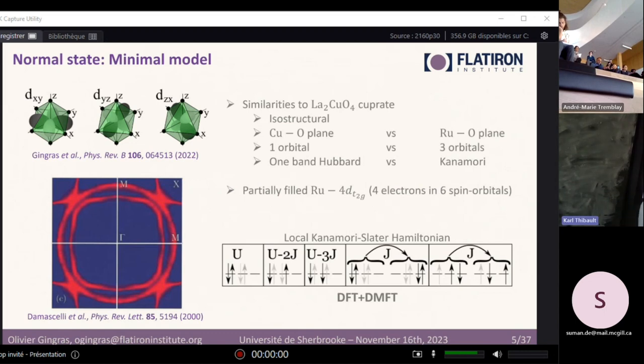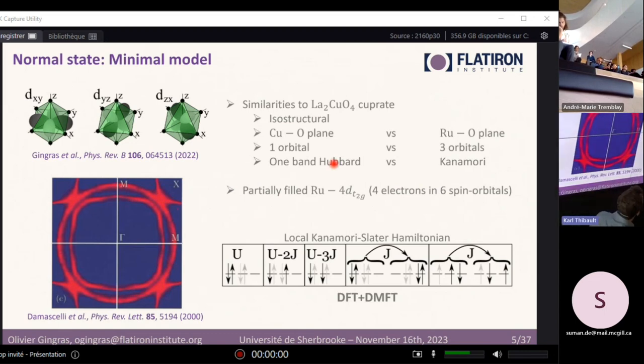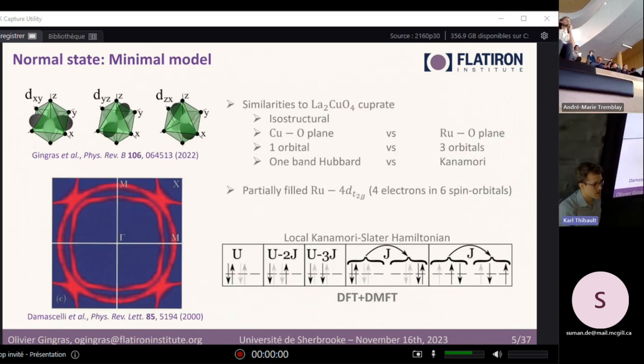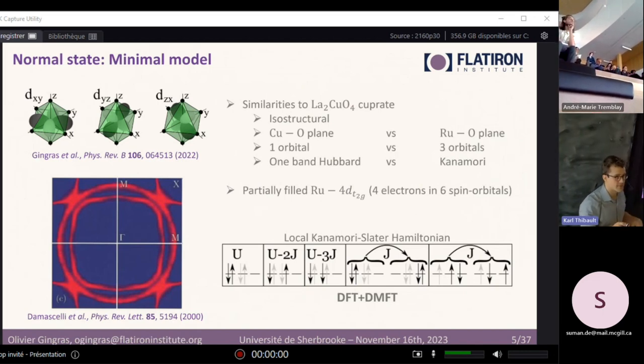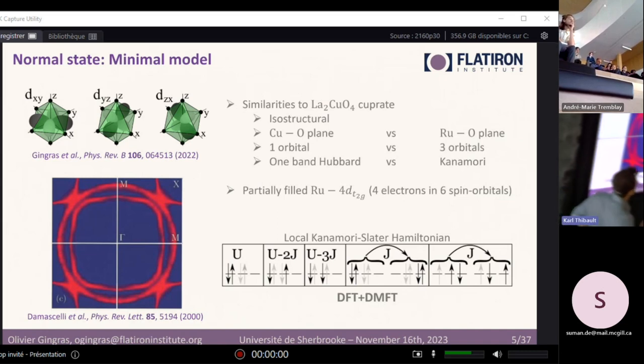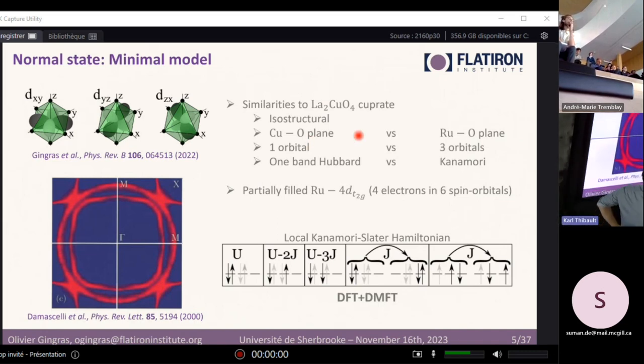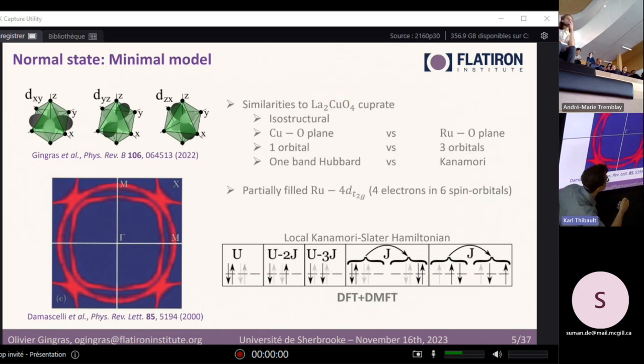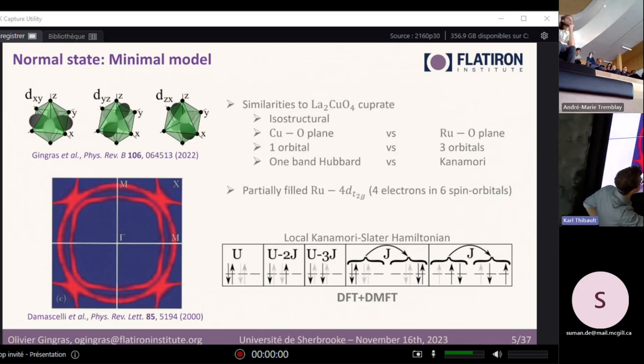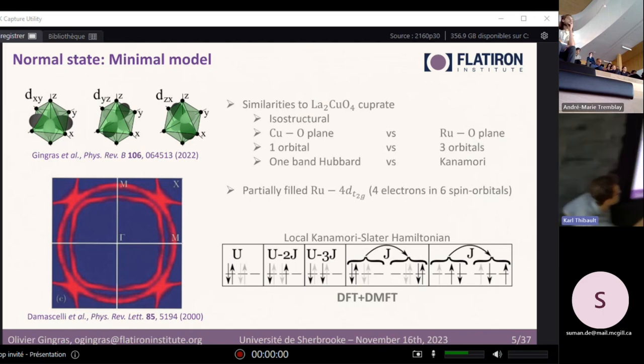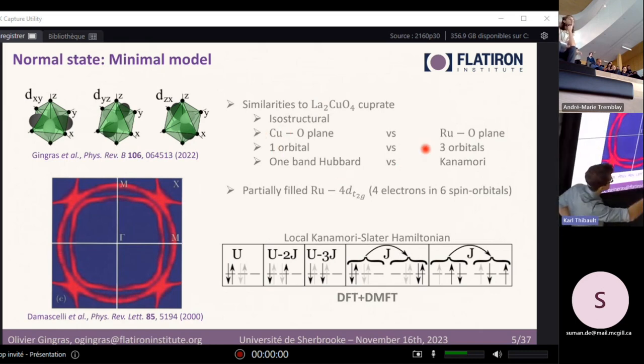As I said, this material shares a lot of similarities with lanthanum copper oxide. Basically, they're isostructural. They have the same point group symmetry, but they also have very similar lattice parameters. Actually, strontium ruthenate was used as a substrate for lanthanum copper oxide before it was discovered to be superconducting. And just like the cuprate, the main physics is believed to reside in the transition metal oxide plane. For the cuprate, it's copper oxide planes, and in strontium ruthenate, it's ruthenium oxide planes.